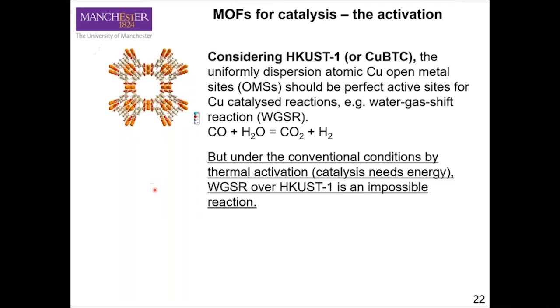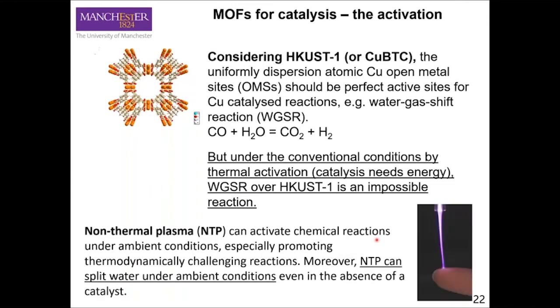So therefore, I have other colleagues working on non-thermal plasma. This is work done back in 2018, I think. We said that if we use non-thermal plasma to activate this, we can potentially activate the water in the gas phase, and therefore preserve the activity of the MOFs and make sure that this reaction will happen. And this time we don't need any heating. So we can maintain the activity and also the stability of the MOF materials for some interesting reactions.